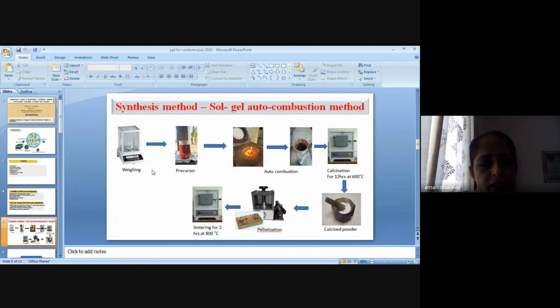This is the synthesis method. They have been prepared by the sol gel auto combustion method. Firstly, the metal nitrates were weighed in the stoichiometric proportion. After that, they were dissolved in water, and the dissolved metal nitrates were mixed with the fuel agent with constant stirring and heating, so that the liquid gets converted into powder. After that, the PVA binder was added so that they bind together to form pellets. And after that, they undergo the sintering process for 2 hours at 800 degrees Celsius, so that the nanocomposites can be easily characterized.